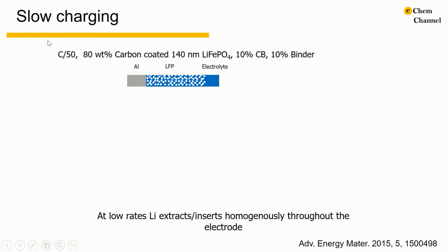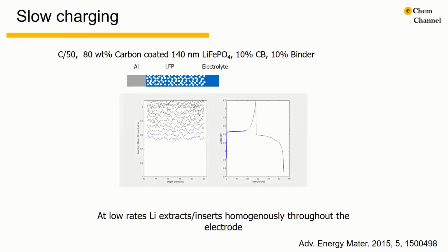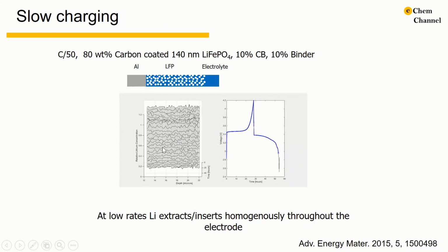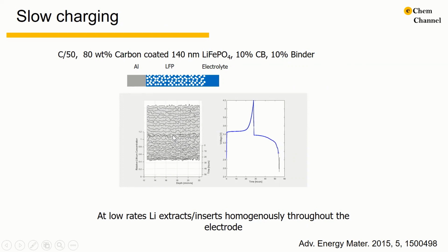Here shows an example when the electrode is charging and discharging very slowly. The electrode is made of 80% of LFP, 10% of carbon black, and 10% of binder. The relative lithium concentration in the LFP is measured as a function of the depth. When the voltage increases from 2.8 to 4.2, the lithium concentration decreases gradually, and when the voltage decreases again, the